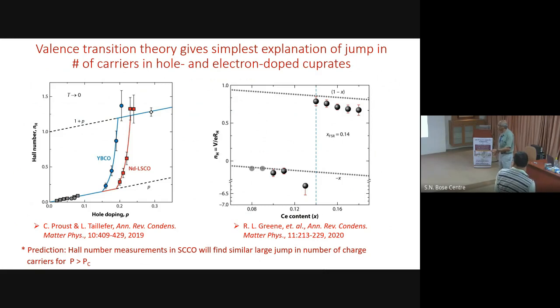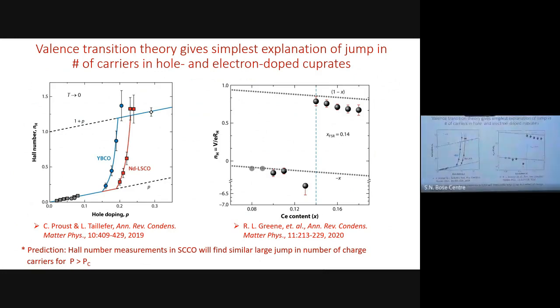What's happening here, if you know the literature, is that we are putting in more and more strontium doping while measuring the Hall coefficient. So 1 over the Hall coefficient, the number of carriers, goes like this. And then you see a sudden jump, which is 1 plus p. Now, let's assume my picture is correct. You have put p holes in the oxygens, and all the copper holes jump to the oxygens. You will have exactly 1 plus p.